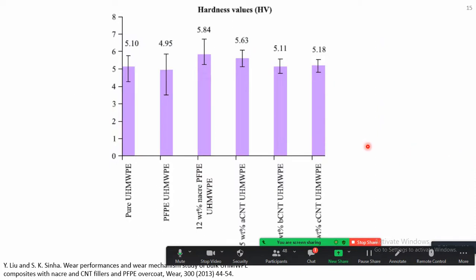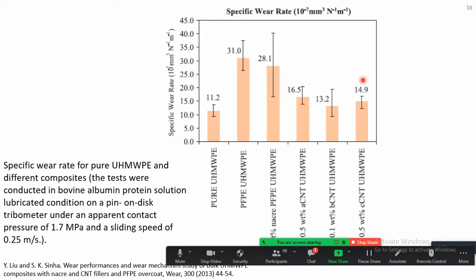Here we see that hardness can be improved by adding fillers, but not by much. Improving hardness may lead to a better specific wear rate, but in our case we found that the wear rate actually increased because of the presence of these fillers. We were a little disappointed that the pure UHMWPE still does better in terms of specific wear rate in bovine serum lubrication.